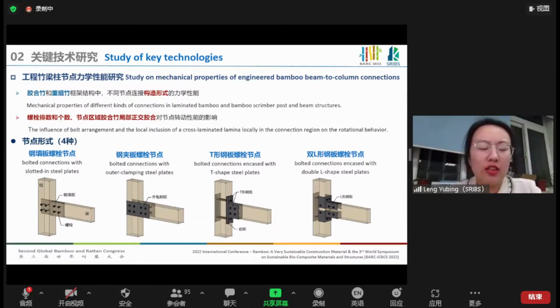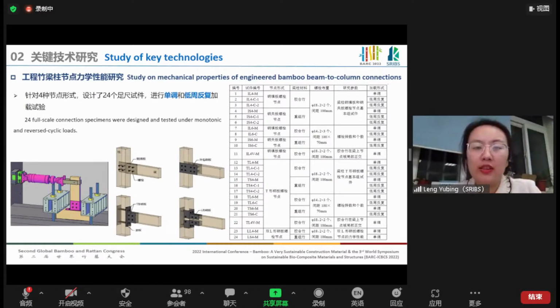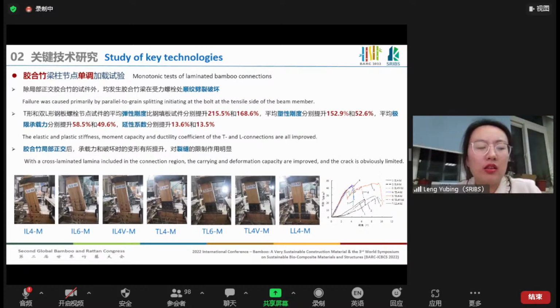During processing, if we use this bolted connection with bamboo scrimber, because it's too hard, it's very difficult to drill the bolt holes. As an alternative, we found we can use outer clamping steel plates. But if we put the steel at the outer layer, there is a fire prevention challenge, so it's not an optimized situation. In order to improve the situation, we came up with cases 3 and 4. One is T-shaped steel plates. The fourth one is double L-shaped steel plates. The latter would consume more steel, but the cost is still very affordable. So we had these four types of tests.